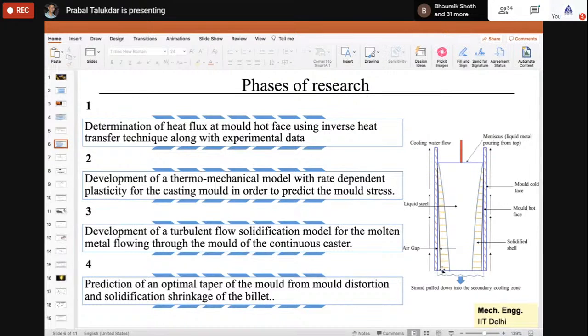Why is it happening? Because this solidified shell is compressed because of the change in density. There is a shrinkage, and because of that there is air gap formation, and because of this air gap the heat transfer is affected. If you make your mold slightly tapered to the inward side, then this air gap will reduce. And if this air gap is reduced, then your heat transfer will be very good. That is why you need numerical simulation to predict this air gap. That's what we have been doing in recent times.